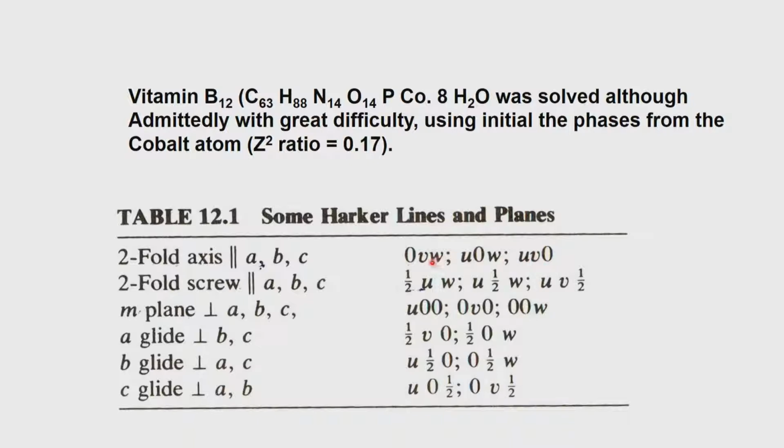So, you see that between the three projections, between these two U is common, between these two W is common, and between 1 and 3 V is common. So, we get a unique solution for UVW. Once we have UVW, then it is in principle possible to get the coordinates of the heavy atom. So, the heavy atom presence will be easily identified by looking at these projections, and also the identity associated with the symmetry information. So, even though symmetry is not there in the overall Patterson, the projection reflections carry information associated with the translational component.